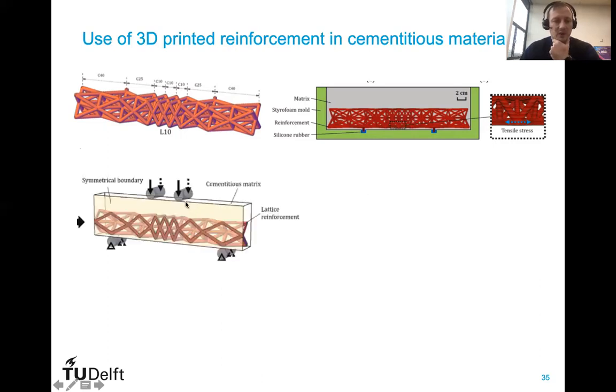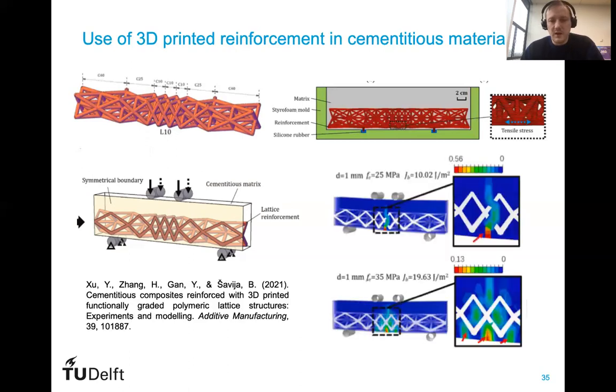So we also created a simulation of this 4-point bending experiment. We use symmetry to cut down on the computational load. And we use, in this case, Abaqus with a CDPM model to simulate the process of deformation and fracture in this material. We can also then vary the properties of the material.